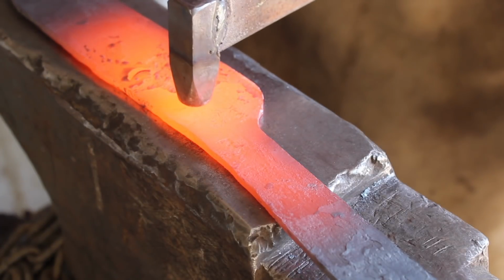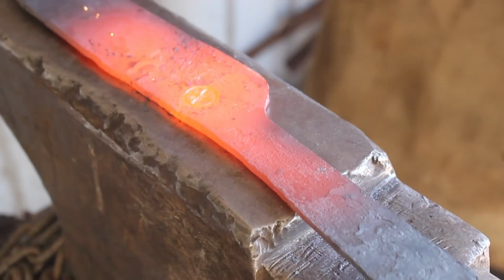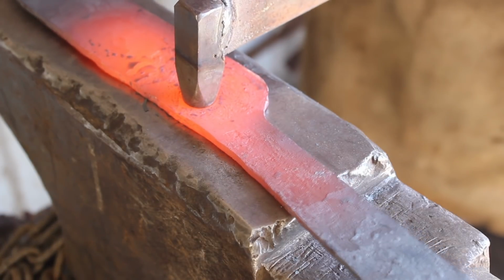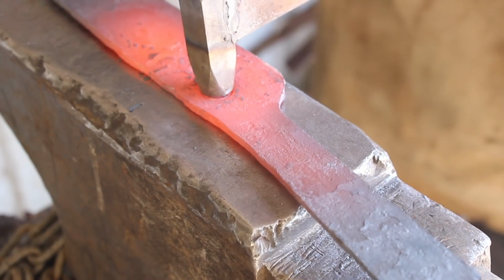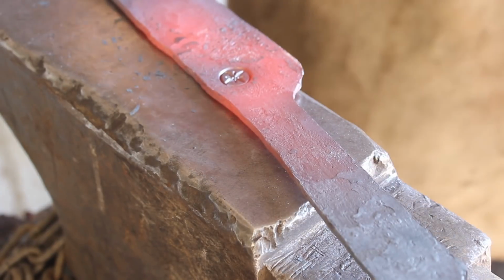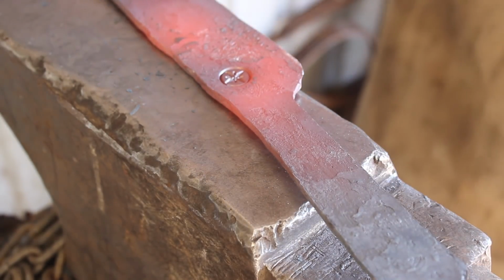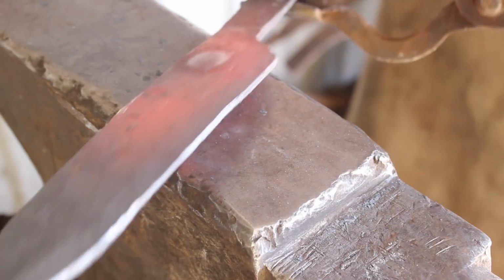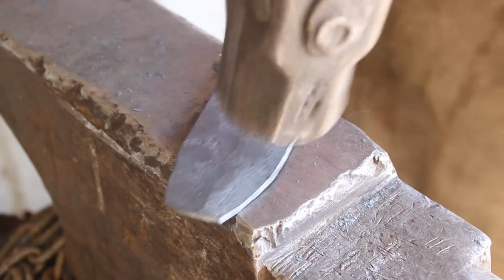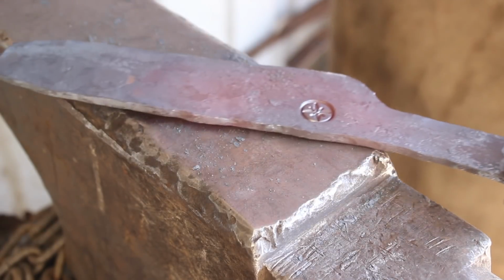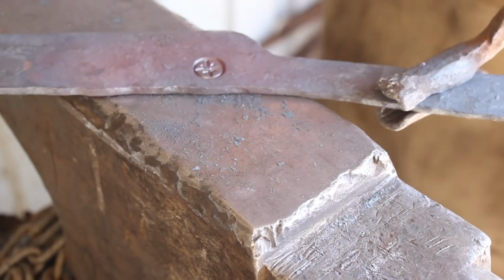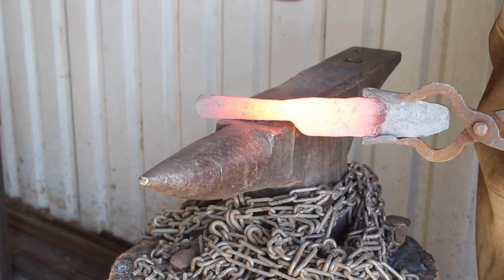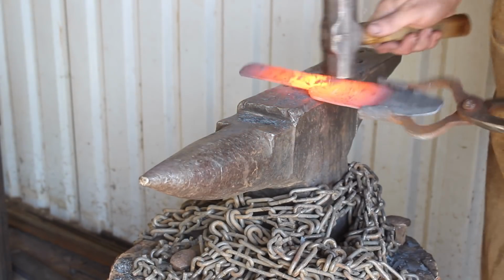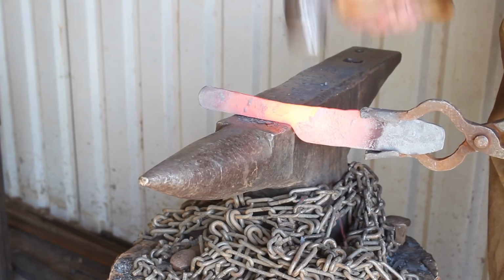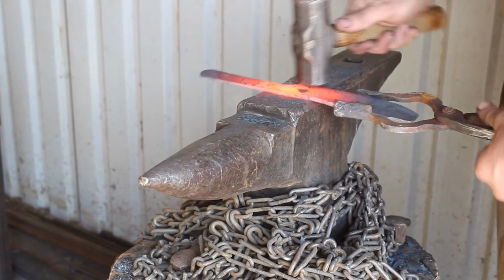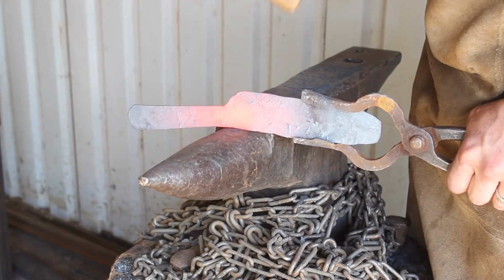One of the reasons that I forged in the bevels somewhat is because, as I mentioned a minute ago, anytime you grind material off, you're changing that pattern. So we have a raindrop pattern, or a modified raindrop pattern here, because of the holes that we drilled in there and then forged flat. But if I then go and grind off those layers of steel that we just worked on, that's going to remove that pattern. So by forging the bevel down a little bit, that's going to give us more leeway when it comes to grinding in the bevel. We don't have to remove as much material and grind through those layers of our pattern.